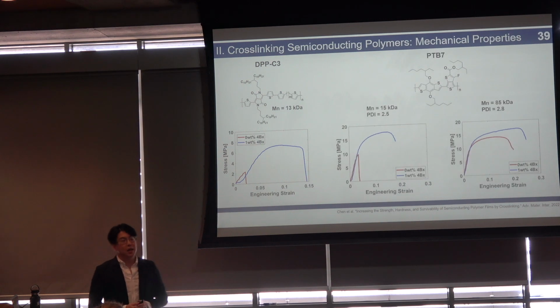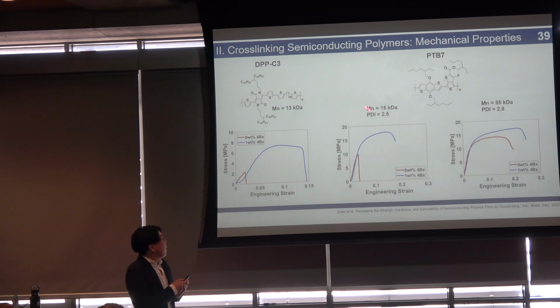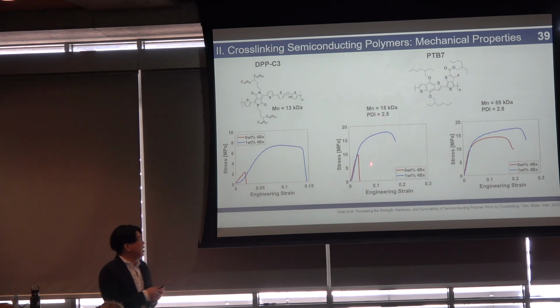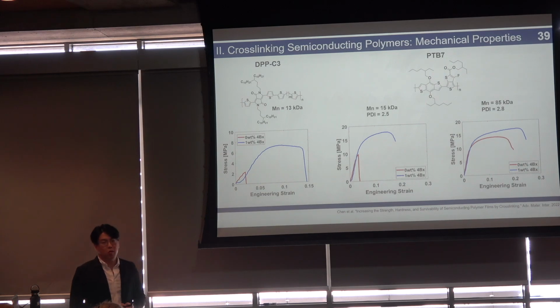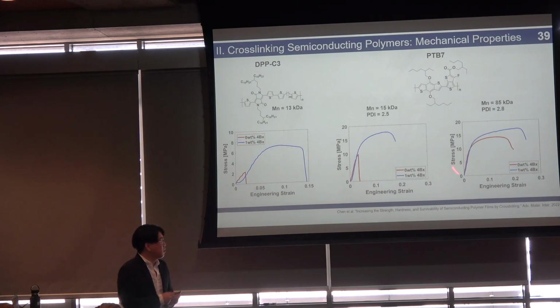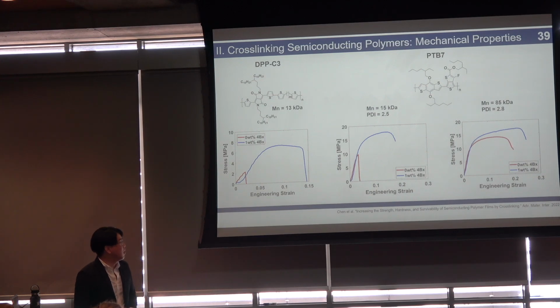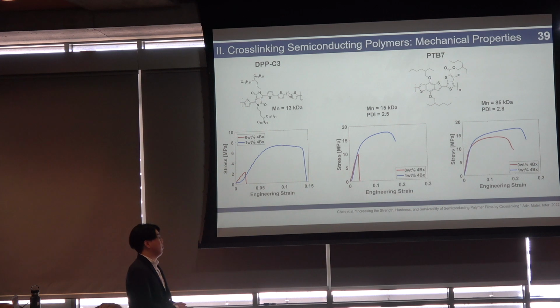And we can verify this by looking at PTB7. And we compare a molecular weight of 15 kilodaltons and a molecular weight of 65 kilodaltons. And again, we see a very, very big improvement for the low molecular weight polymer, even though, sure, there is some improvement in the high molecular weight material, but there is a bigger relative improvement for the low molecular weight material.